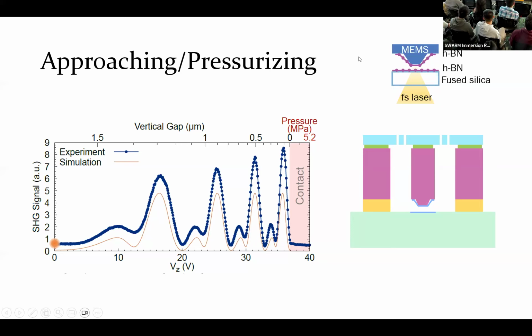And we're shining in a femtosecond laser from the transparent side, and we're monitoring the generation of blue light from the red light in this experiment. As you can see here, we're changing the voltage on the z-axis actuator, which brings the 2 layers of hBN closer or farther apart. And as we're doing that, we're seeing this oscillation in the second harmonic generation signal.